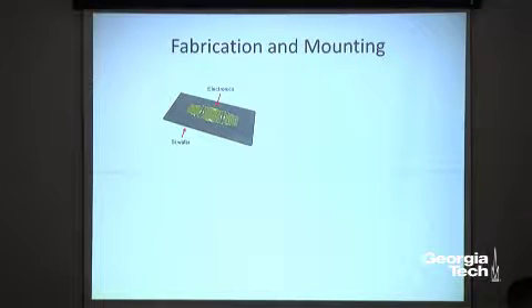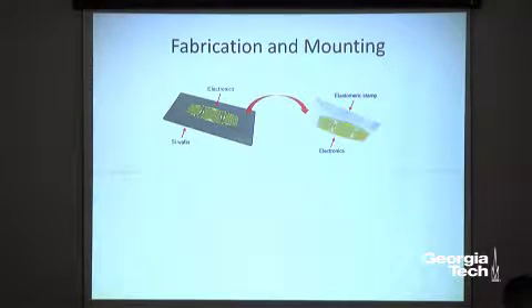Instead of having the conventional processes right on this silicon wafer, we add a polymer membrane, ultra thin, about 200 nanometer thick PMMA. We coat it before metallization or lithography. Then after finishing the pattern, we dissolve that polymer membrane. Then we can dissociate these electronics from the silicon wafer by using a sticky elastomeric stamp or water-soluble tape, or anything that you like. Something sticky, right? Then you can dissociate this, which was floating from the carrying silicon wafer. And now you can play with this electronics for many different things.